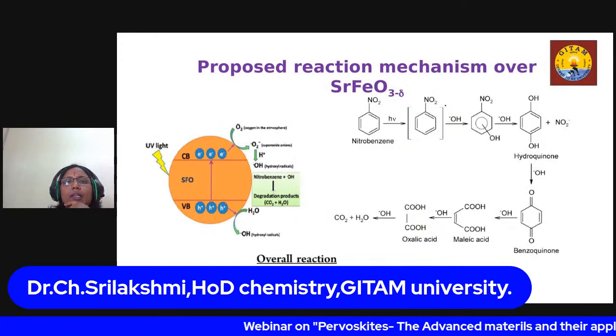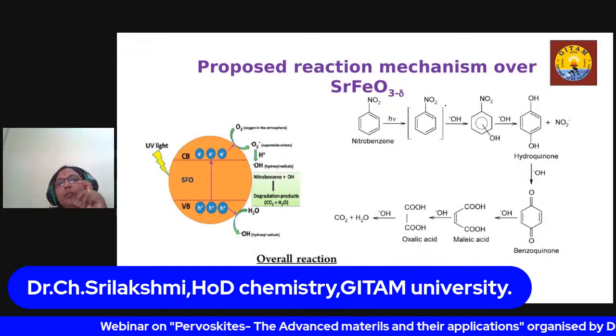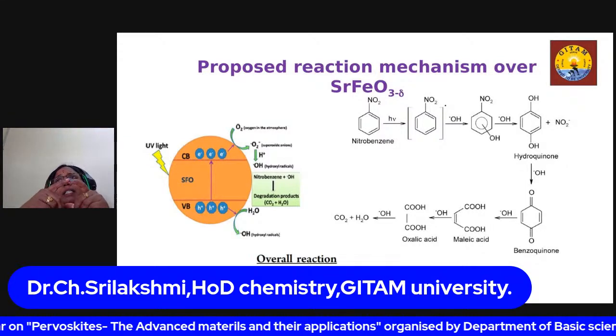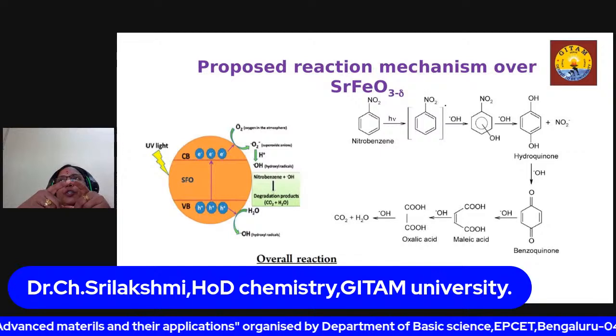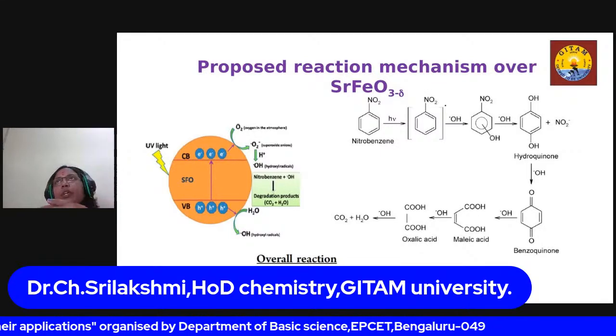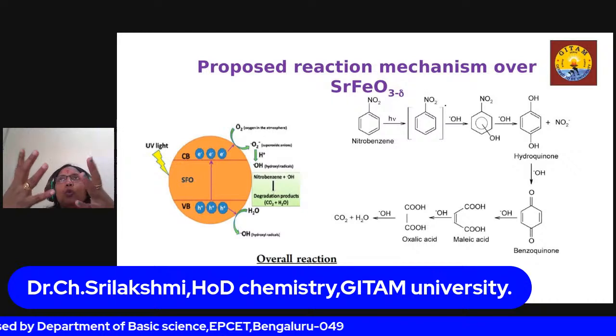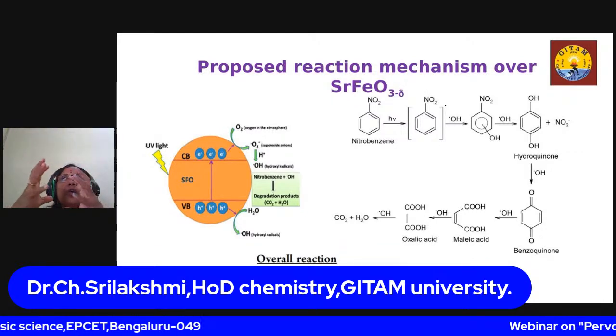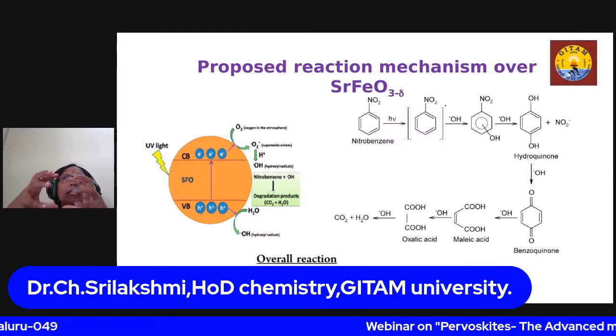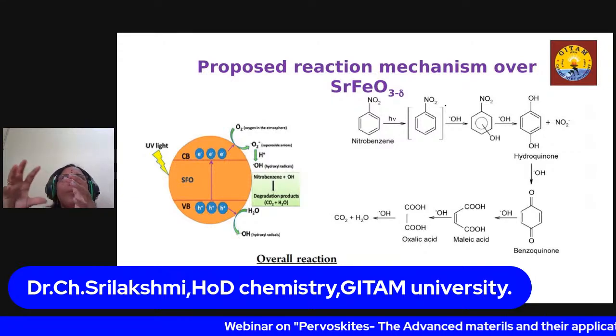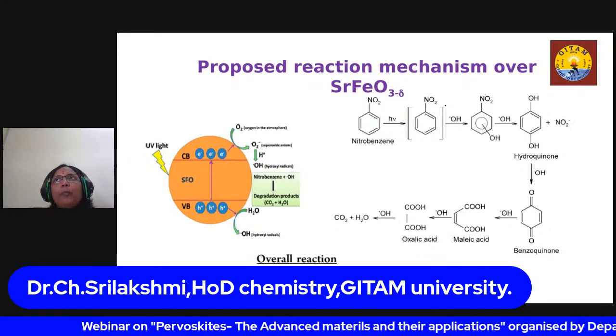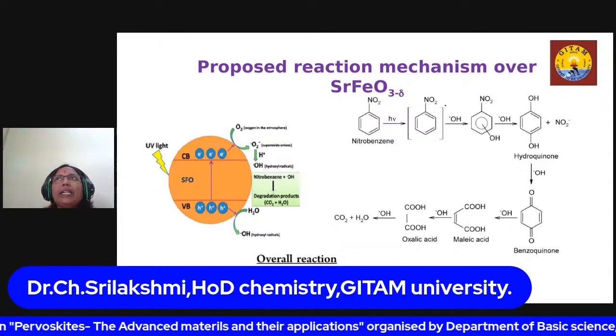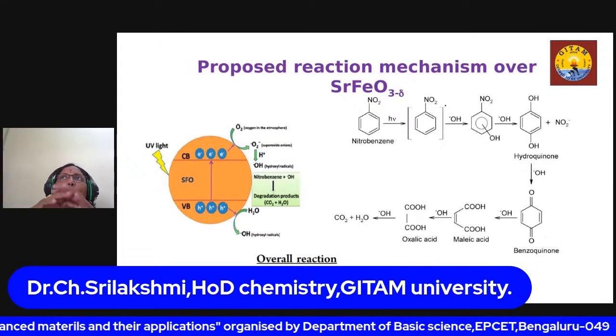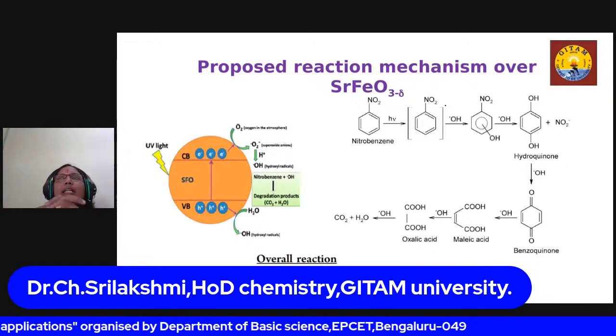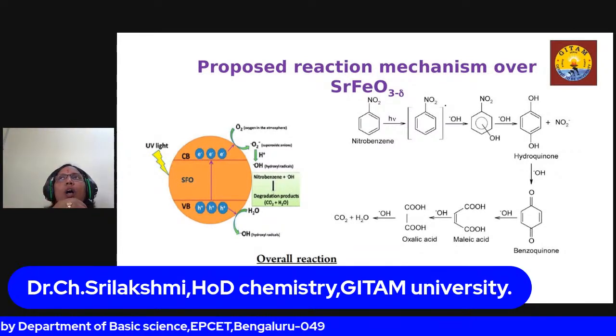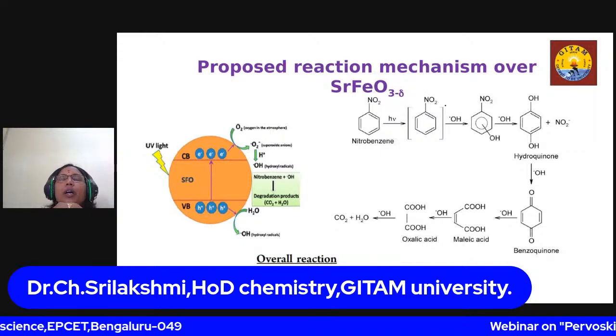Then what I propose is that the reason is what is happening in the presence of H2O2. Excess hydroxyl groups are there. These excess hydroxyl groups interact with the dissolved CO2 in the solution and form bicarbonate. Bicarbonate is converted into carbonate, and this carbonate that is formed gets reabsorbed on the catalyst and blocks the active sites. That's the reason why the degradation is low with H2O2 over the catalyst.